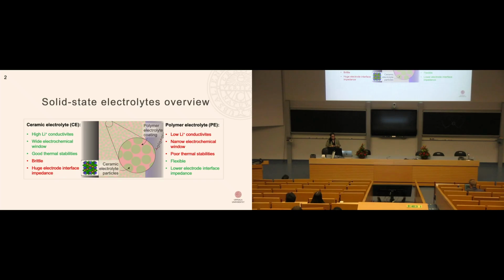Solid-state electrolytes are really a broad range of materials where we on the one hand have inorganic ceramic crystalline materials, and on the other hand we have soft, flexible polymers, which tend to have much worse possibilities of ion conduction compared to the ceramic materials. And we also have composite materials mixing both of these materials to improve the flexibility and the mechanical properties of the material, in addition to the ion conductivity. In these different materials, the diffusion mechanisms are very different, and so they also require quite different approaches to be able to understand and optimize the conductivity.